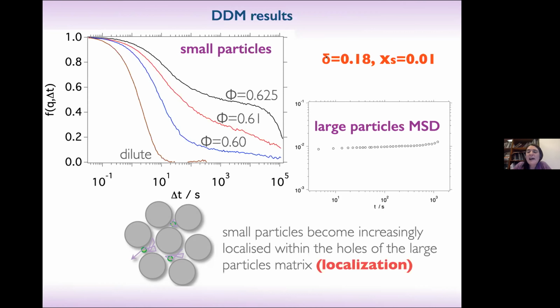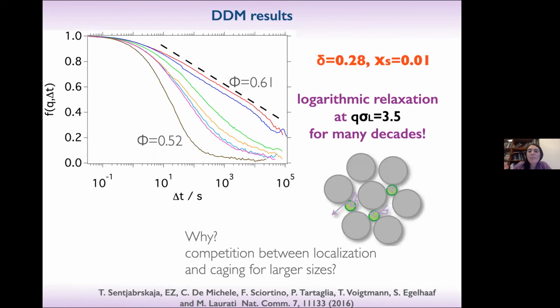Okay, so at low delta, this was the scenario, but then the surprise is that for delta 0.3, they were very lucky with the experiments: at this Q vector, they found the onset of a logarithmic decay for a huge amount of time, like 4 decades. And so we started to wonder what it was due to. I mean, was this a higher order singularity in this model?